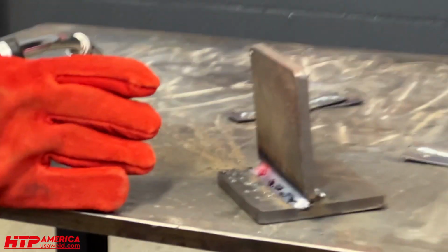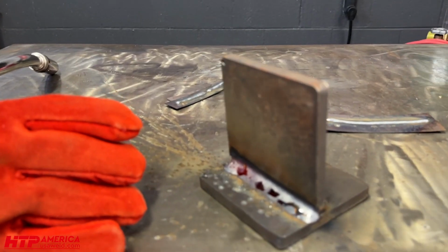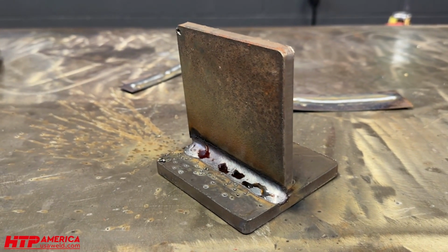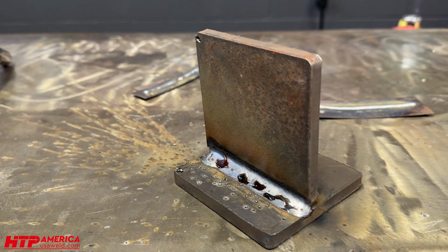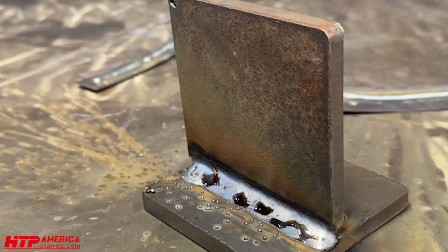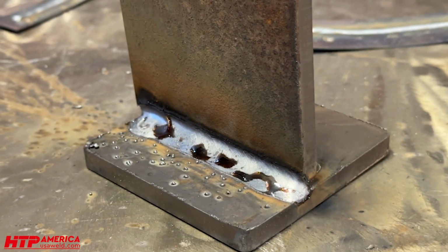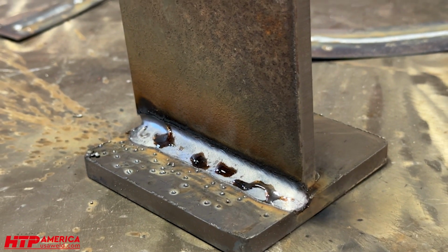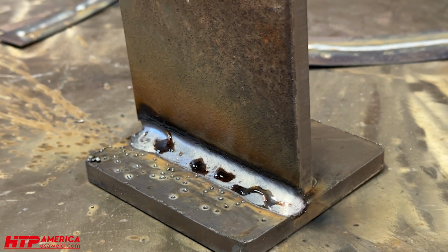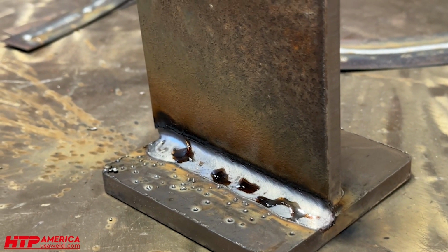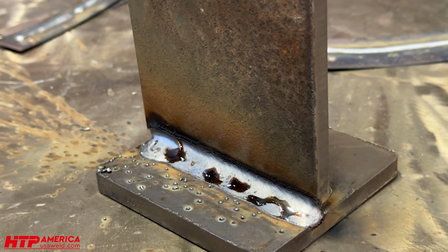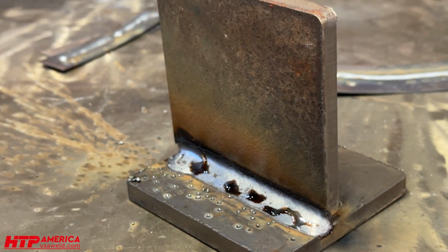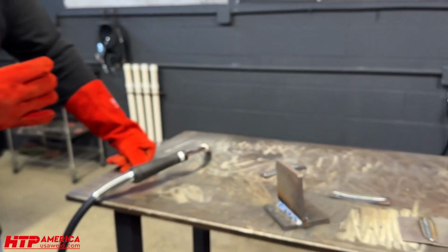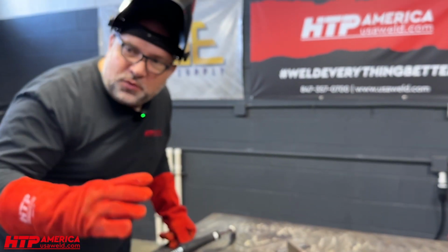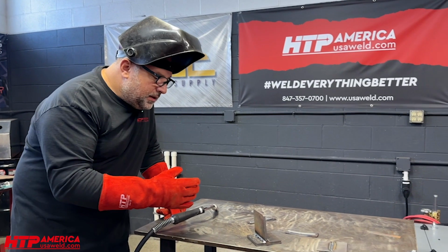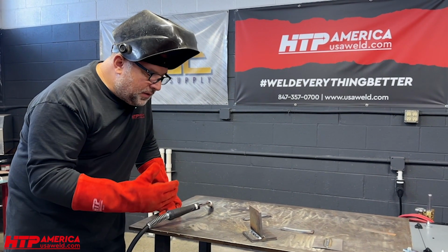So this clearly was 100% spray arc. Now you do see a few BBs down here. Again, intentionally, no prep, no anti-spatter spray. The reason you see those BBs here is because you hear a couple pops and cracks. That's the 75-25 gas we're running. If you run at least 80% argon and less than 20% CO2, you don't have this, you get into a clean spray arc. That is the difference between being able to get into a clean spray arc with the proper gas or using 75-25 gas.